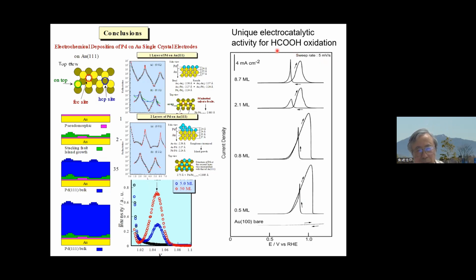This is the electrocatalytic activity for formic acid oxidation for 8 monolayers and 0.5 monolayer. And this is the bare gold surface. Of course, the bare gold surface is not active for formic acid oxidation. And the 8 monolayer behavior is very similar to bulk palladium. However, in the case of 0.5 monolayer, the activity is actually higher and a much higher peak was obtained. So the first layer is quite different from bulk palladium.